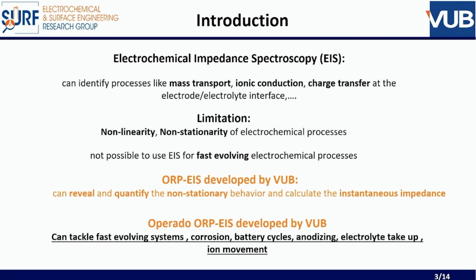because due to the computers and all this software, people are not considering sufficiently non-linearities and non-stationarities, which are intrinsically in your electrochemical process, especially if you look at the corrosion system. The software is completely neglecting that, and this leads to wrong interpretation and even wrong equivalent networks. So I will introduce this kind of impedance measurements that we are doing to come to what we call, and this is the last thing that we have developed, operando impedance.